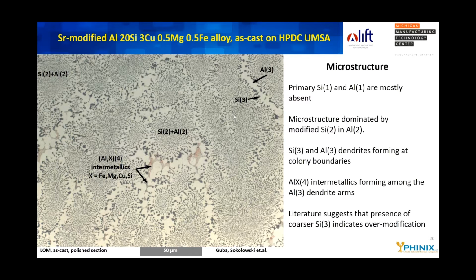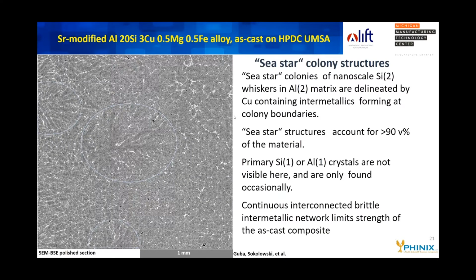Those Si2 whiskers form in colonies, which we call sea star colonies, which we'll see in a second why. And at the boundaries in between those colonies, we find a little bit larger Si3 crystals and the Al3 dendrites, very reminiscent of what Hellawell was showing for sodium modified material. And the intermetallics then form again in between the aluminum dendrite arms at the cell boundaries. So again, we are hoping that those Si3 materials are due to the over-modification, as the literature suggests.